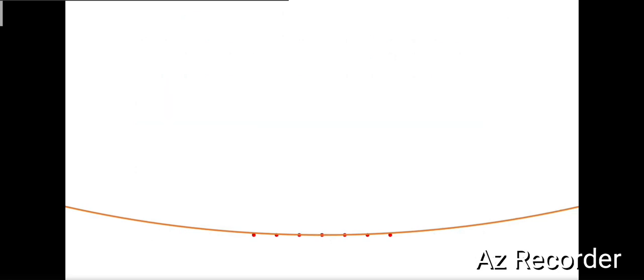So let us look at that Ewald sphere with the lattice points lying on it. The reciprocal lattice points which lie on the Ewald sphere correspond to planes which satisfy the Bragg condition of diffraction. So for each of the lattice points here, there will be a corresponding diffracted beam. If I have a recording surface parallel to the Ewald surface, then on this recording surface, each beam corresponding to these reciprocal lattice points will be recorded as a diffracted spot.